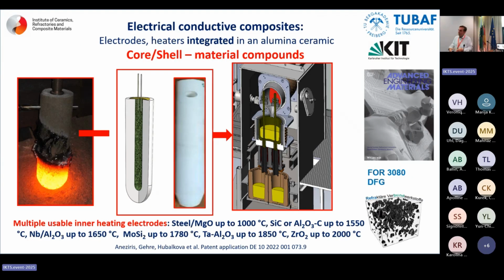And if you think like this, yes, I showed you in the beginning this self-glazing carbon bonded alumina, stopper, electrode, whatever you want to do. What would be if we take the carbon bond, and we put it inside as an electrode? And we leave alumina outside, because alumina will not have the interactions with the steel and create alumina inclusion.